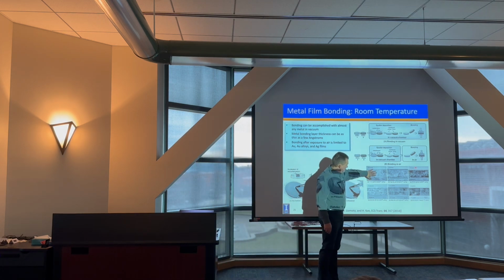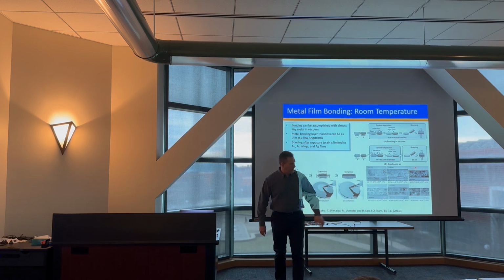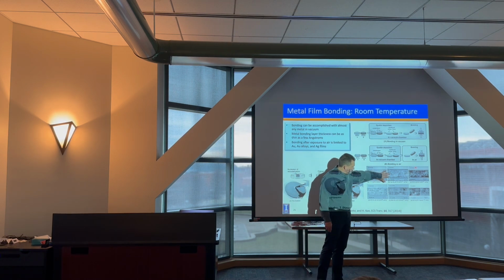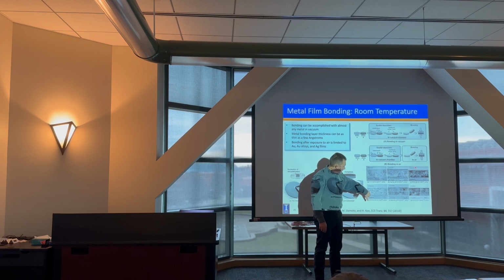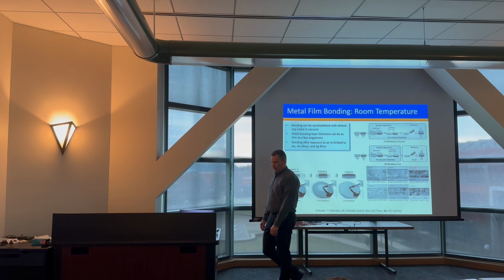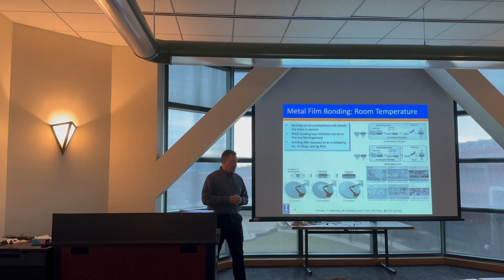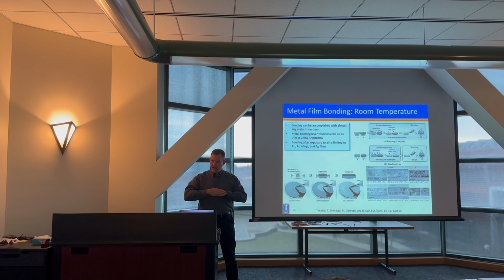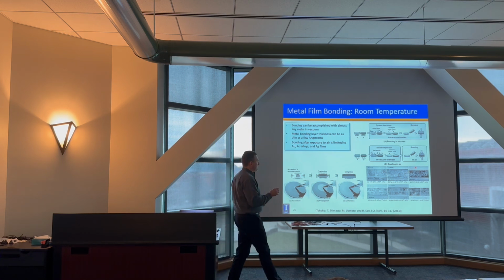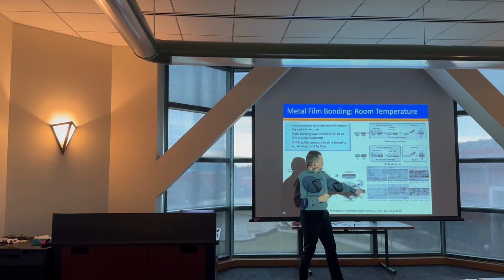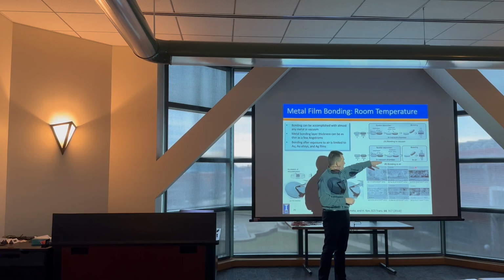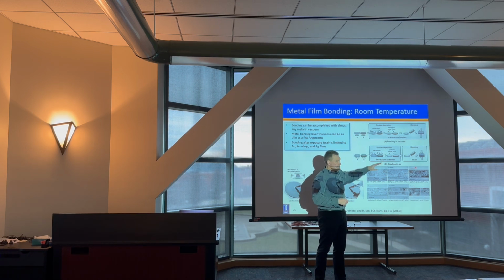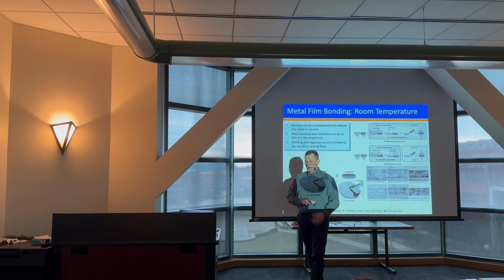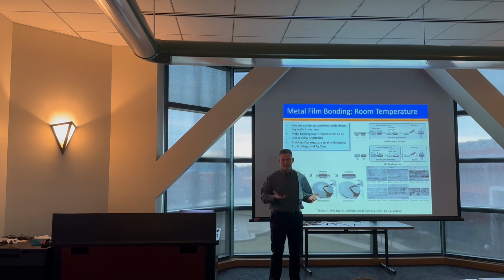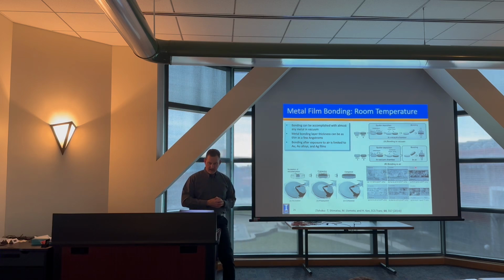But if you look at systems that people have demonstrated this in, they've done it with titanium, silver, platinum, chrome, moly, tungsten. All of these have been used to form these metal bonds, which are high quality, but they have limitations with regard to the sort of apparatus that you need in order to do this, because you need to be able to do it in vacuum, you need to be able to clean your surface, you need to be able to flip, you need to be able to align and bond. So again, doing something like this requires the same sort of cluster tool that we saw in the previous slide.